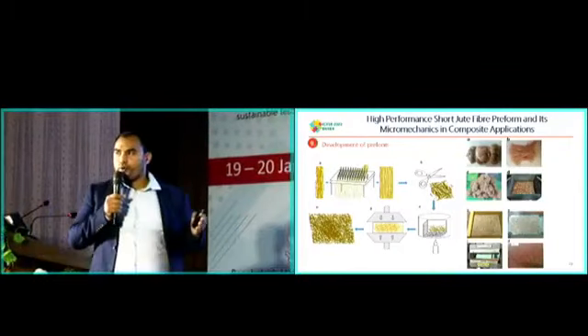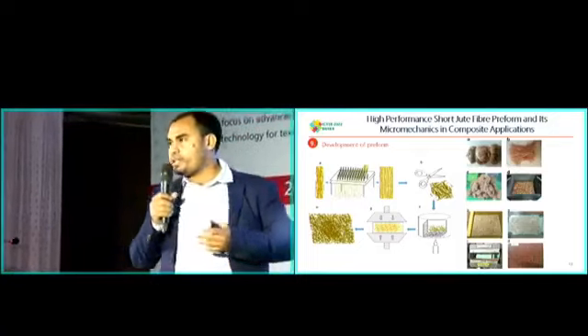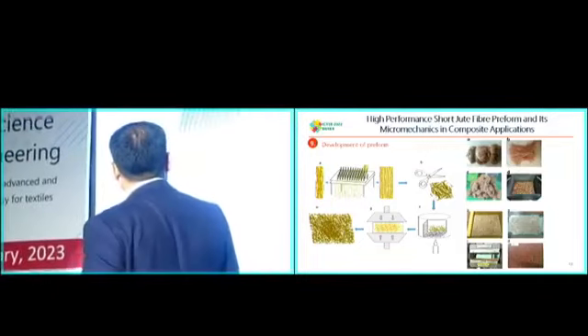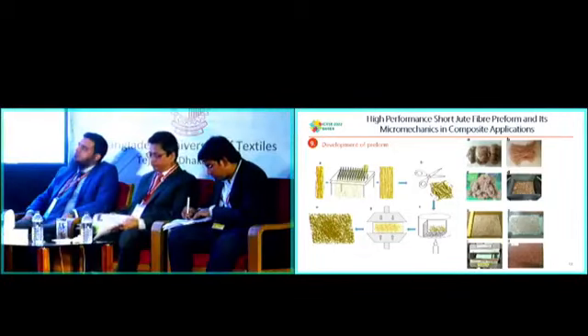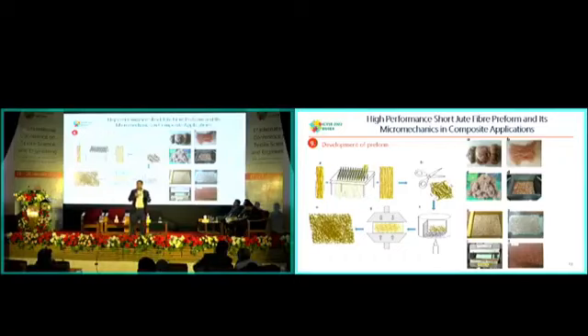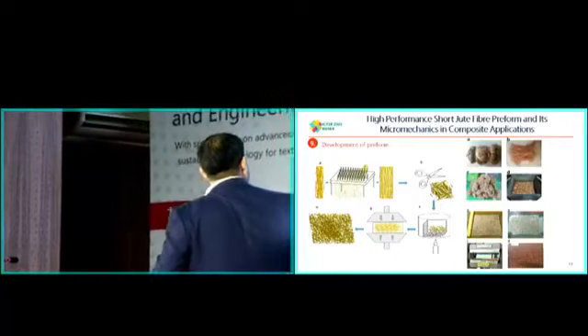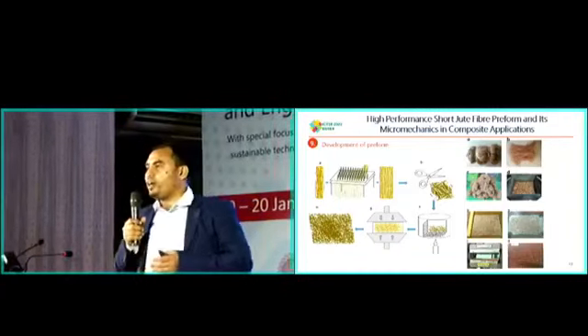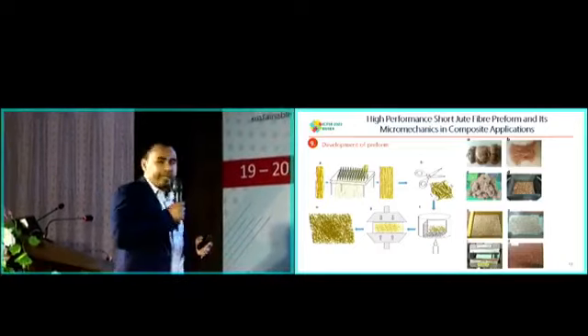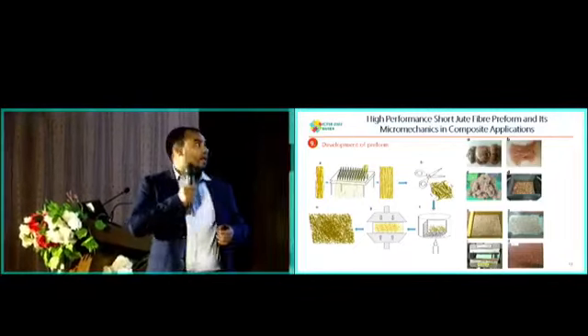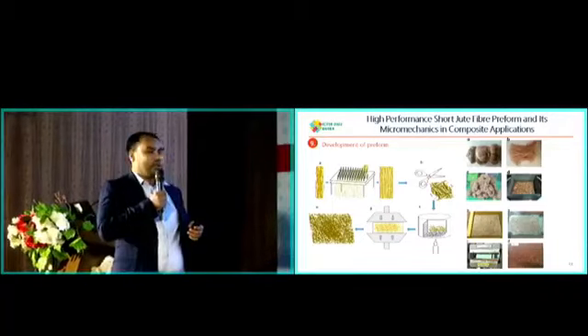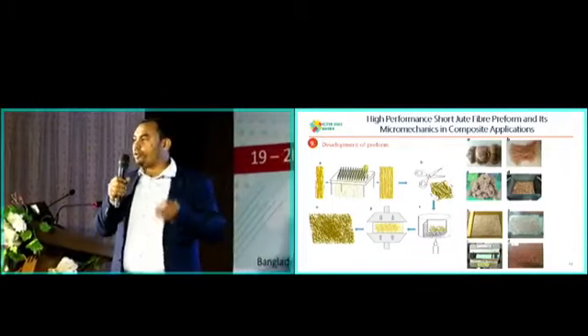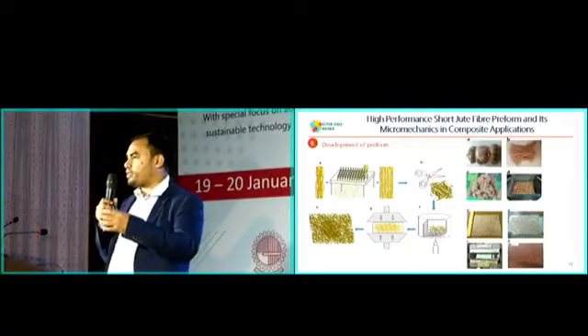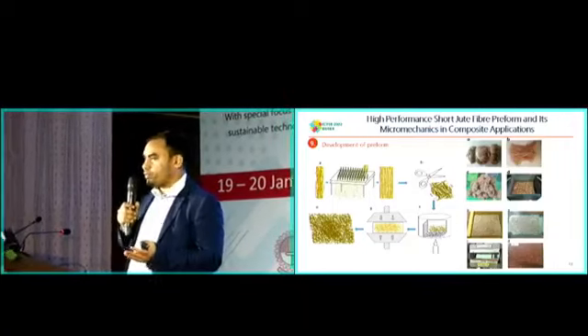So let's talk about the development of the preform, how we developed this preform. As you can see from the figure, we collected the virgin fiber or the field-retted fiber, and then we applied the mechanical extraction, using in-house made laboratory equipment. Then we got very highly individualized field-retted jute fibers. Basically, all the fibers are at the elementary stage. Then we cut them into different lengths, and we also developed a cake-producing device so that we can collect the fibers in a uniform way. This is also a laboratory-made device.